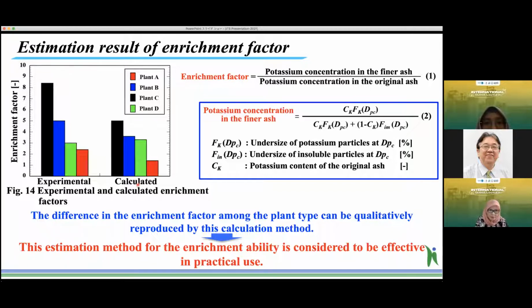The comparison between the measured enrichment factors and those estimated by this method for 4 plants is shown in figure 14. The left is experimental data and the right is calculated results. The calculated enrichment factor does not quantitatively agree with the measured values. However, since the difference in the enrichment factor among the 4 plants can be qualitatively reproduced by the calculation results, I think this method is effective in practical use.